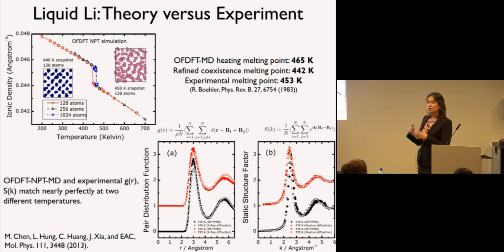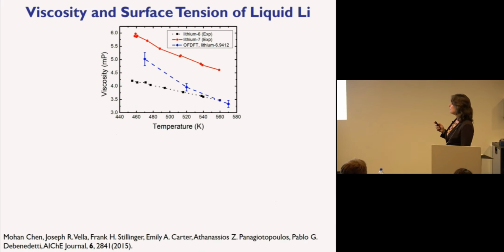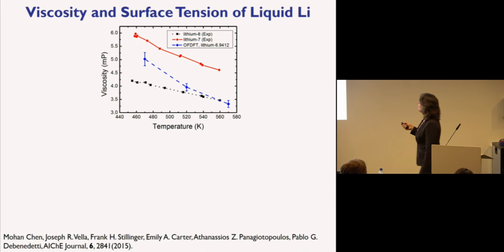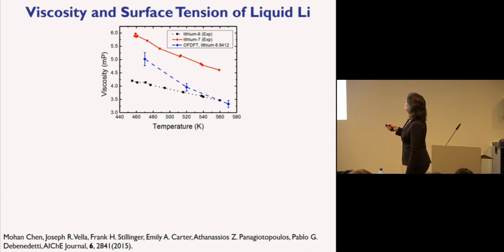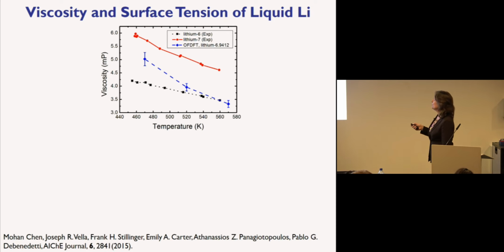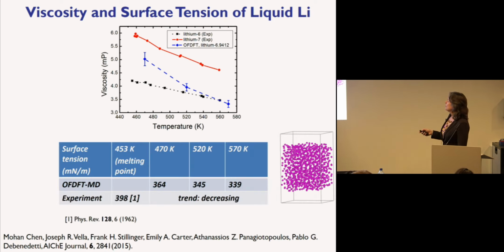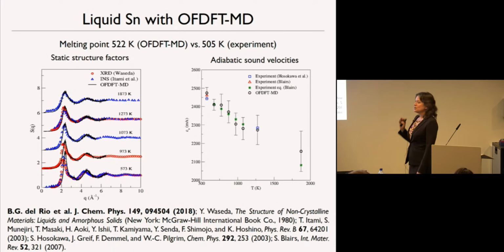So anything that looks nearly free electron-like, that's fairly smooth in the density, we can do a good job describing. This just shows you another property, viscosity as a function of temperature. These are pure isotopes, so this is lithium-6, lithium-7. We're doing something that's closer to lithium-7. It's off, but it's at least within the range that's expected. We can look at surface tension. We looked at a liquid lithium film. We can look at that as a function of temperature and calculate the surface tension and see that it decreases with temperature, which is what is expected, and that's also seen experimentally. The numbers are consistent with one another. We can also do liquid tin.